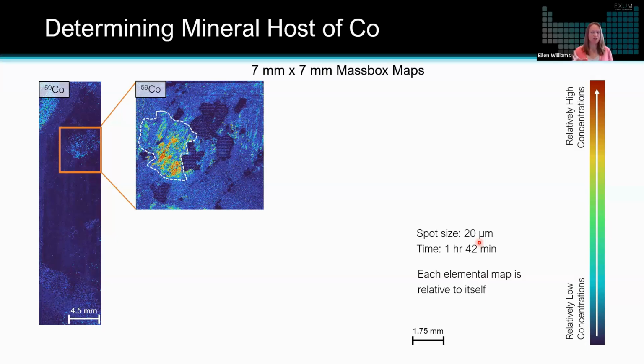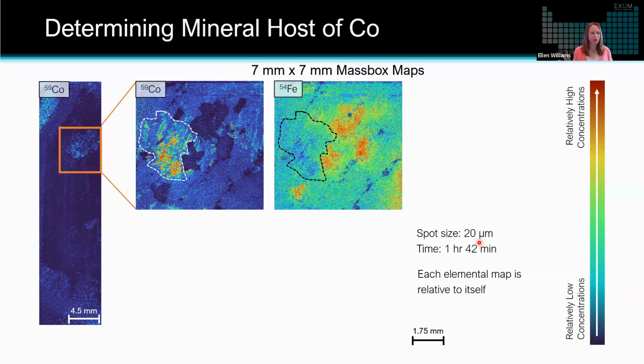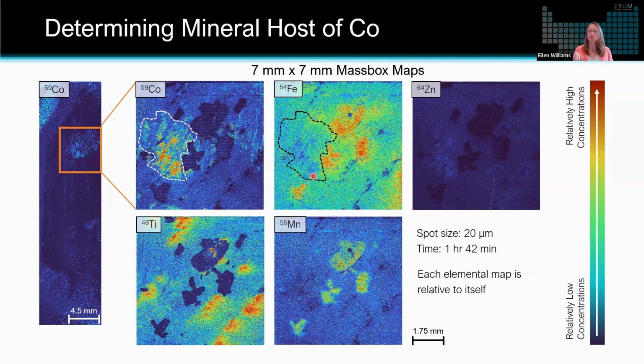So clearly there are some areas of this sample with relatively high amounts of cobalt. And then we can take a look at some of the other elements like the iron and identify that there's relatively low amounts of iron where there's high amounts of cobalt. We can also see how the titanium is distributed. We see that there's relatively low amounts of manganese. So all of these major elements help us understand what mineralogy is hosting this cobalt, which is the element of interest here.